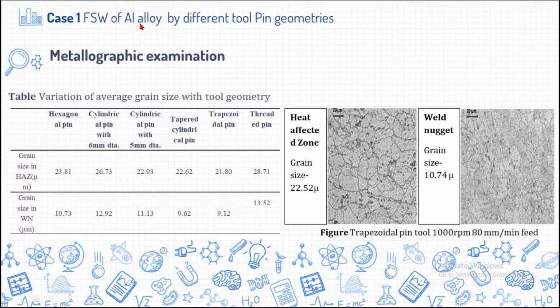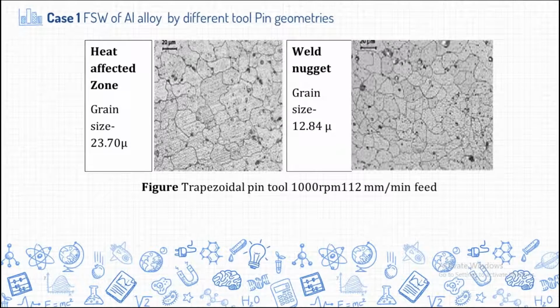In this particular welding, we conducted some microstructural examination at the heat affected zone and weld nugget zone at the center of the zone. If we see these grains, the smaller grains, grain refinement takes place over here for this particular trapezoidal pin. If you see the different pin shapes, these are the grain size values we got at the weld nugget at the center of the weld and at the heat affected zone. From this, it is preferable to have a fine grain structure at the center of the weld. These two, the trapezoidal or tapered cylindrical pin tools, are giving good grain refinement at the center of the welding. So this is about a trapezoidal pin for 112 millimeter per minute parameters. These are some microstructural observations.